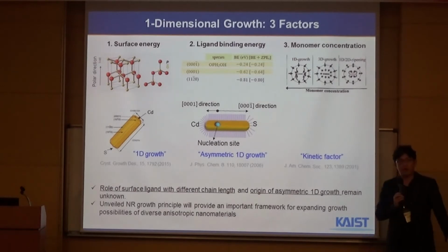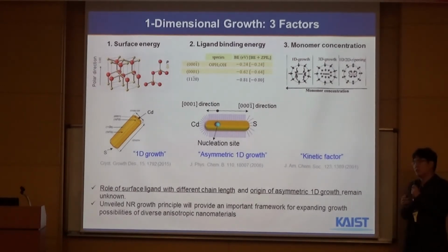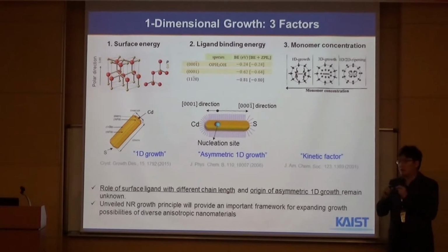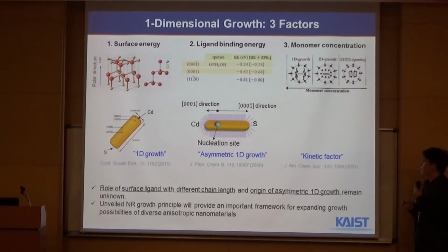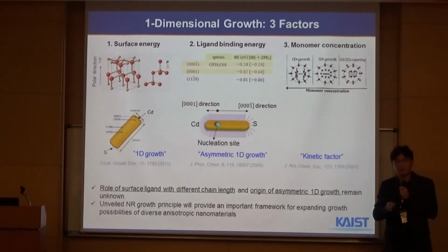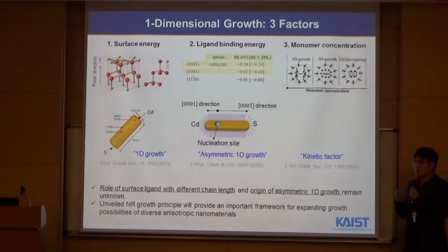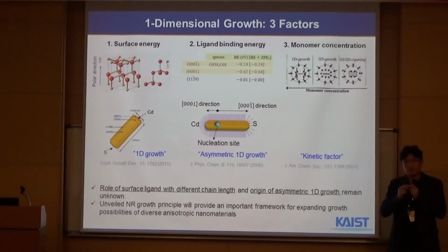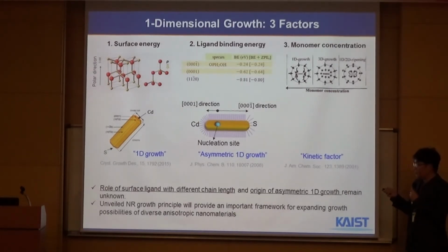And we have some data primarily on the polarized emission, but today I'm going to discuss the growth of these one-dimensional nanocrystals. So for this, we had to use cadmium selenide, not indium phosphide, because of the crystal structures. Which I mean that you need some hexagonal structure or anisotropic crystal structures of material to grow one-dimensional like this. Now, to grow one-dimensional crystals like this, you need to have some motivation or some driving force that creates anisotropy in growth directions.